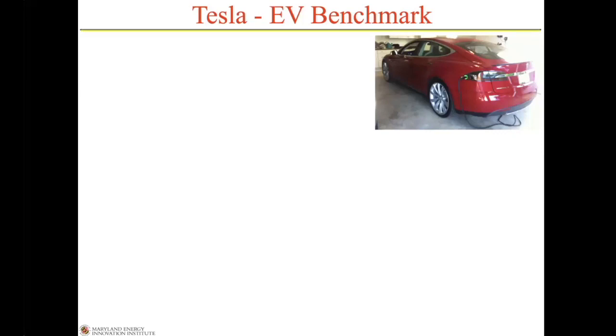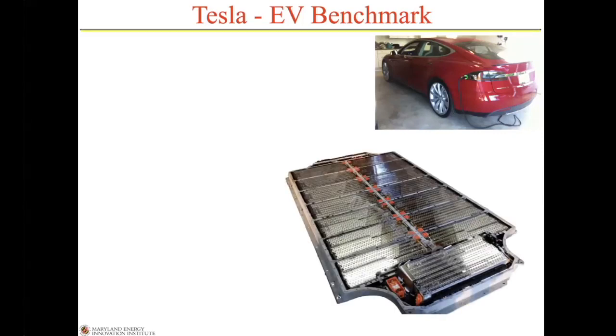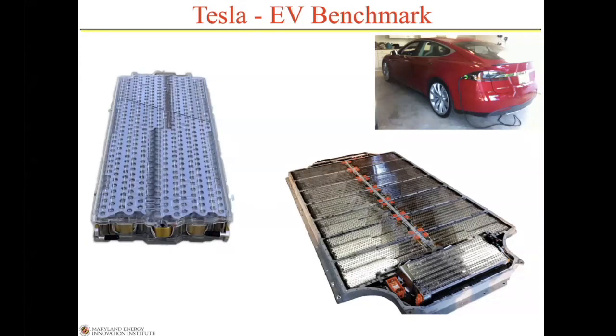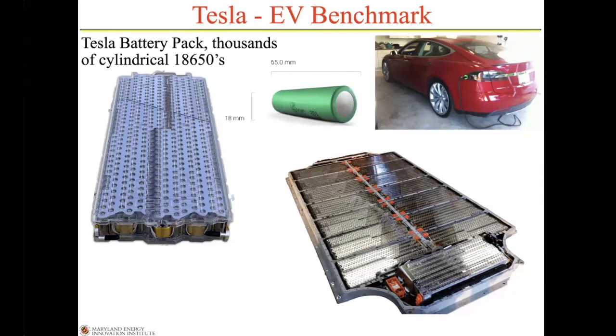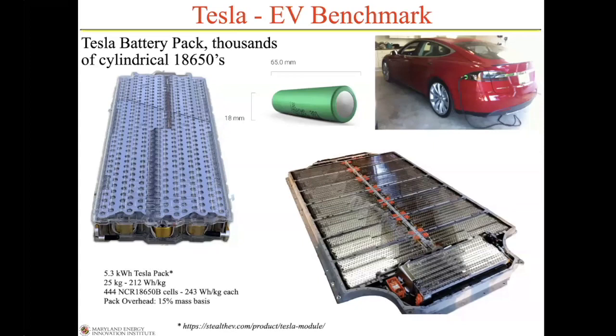And if you were to look at the batteries in that Tesla, they would look like something like this. And each of those packs that you see there fit in the carriage under the car. And what he did is he really just took thousands of what are called 18650 batteries. And you can see the image of one there. They're 18650s because they're 18 millimeters in diameter and 65 millimeters in length. And they're just put in series inside of this pack. One of the issues, though, is that because of this, there is a loss in energy density. So these are NCR 18650 cells from Panasonic, and they're 243 watt hours per kilogram for the cell, but the pack is about 212 watt hours per kilogram. And so there's what we call a pack overhead. That's the loss or the additional mass due to all of the packaging to have all of these cells. It's about 15%, and that's on a gravimetric basis.